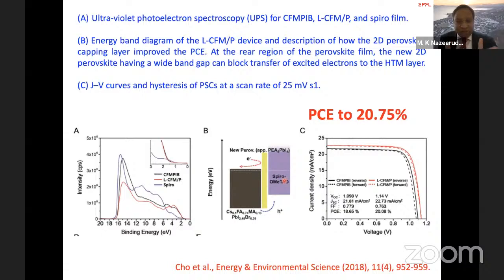So what is happening at this interface? Just imagine for one second that we are effectively reducing the recombination at this interface by pushing the electrons towards the ETL layer, and by pushing the positive charges toward the hole-transporting material.